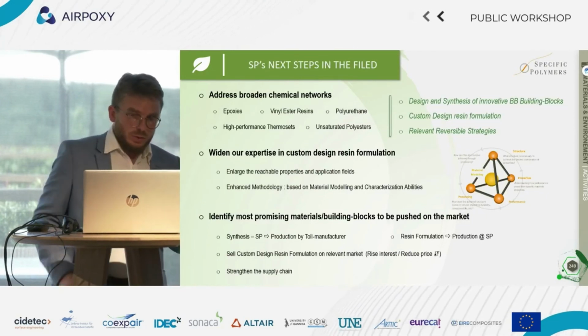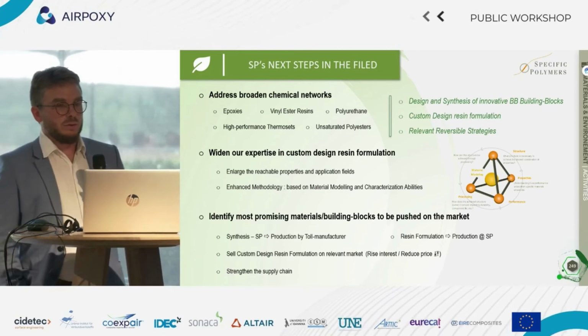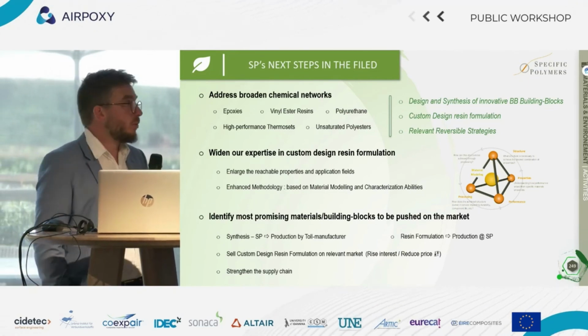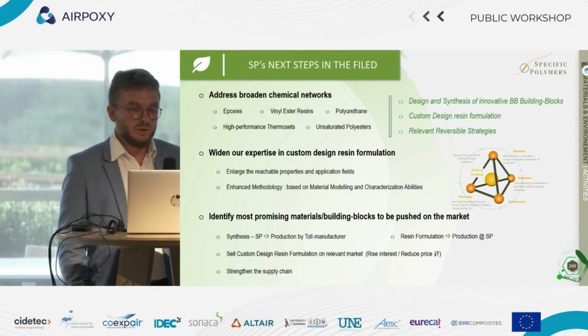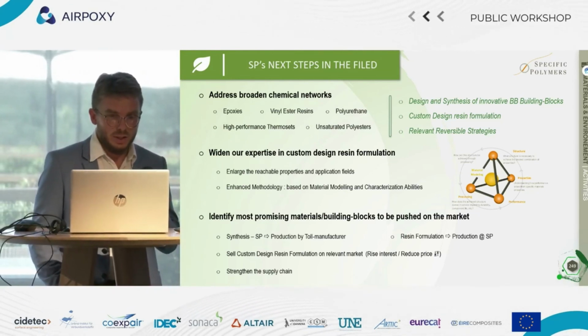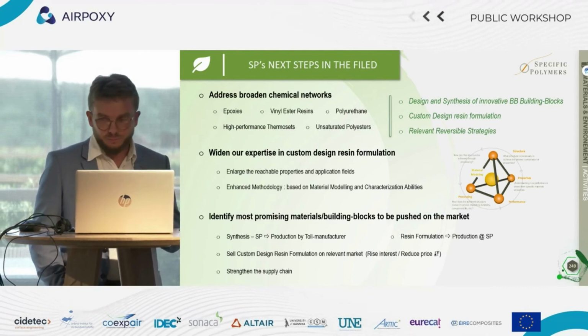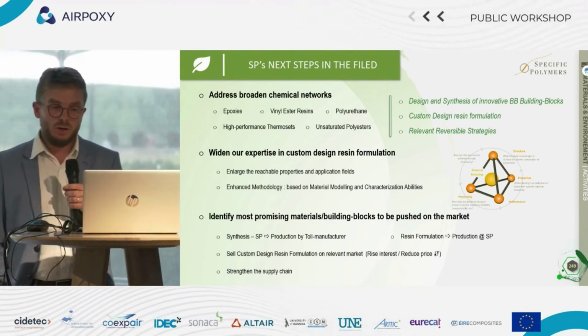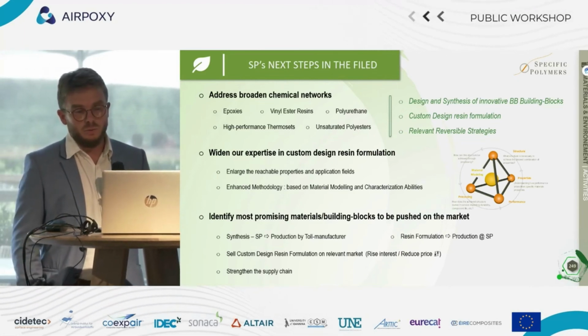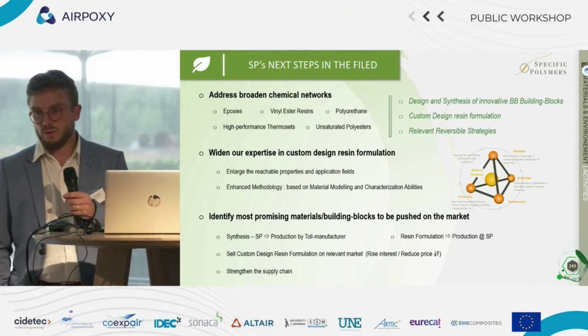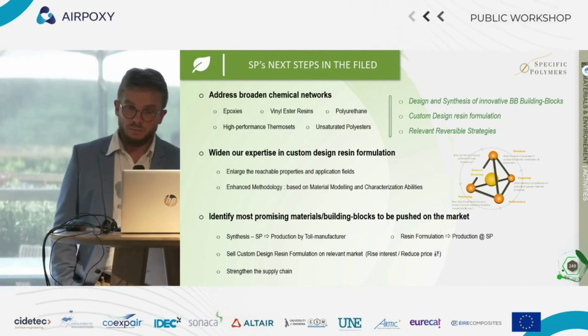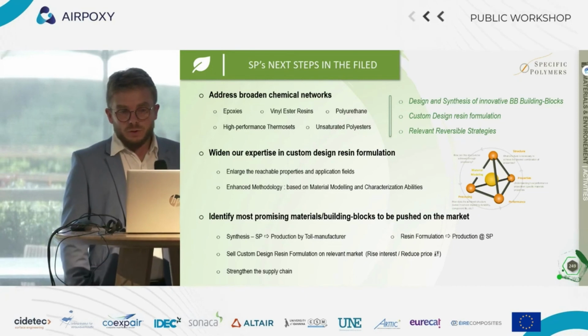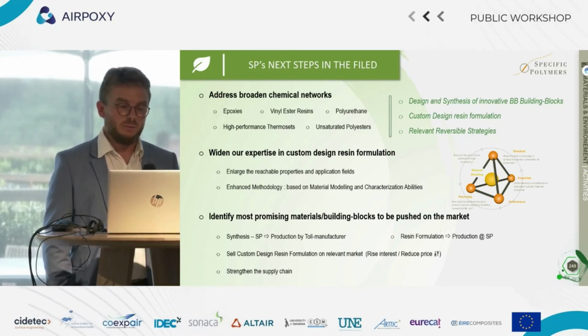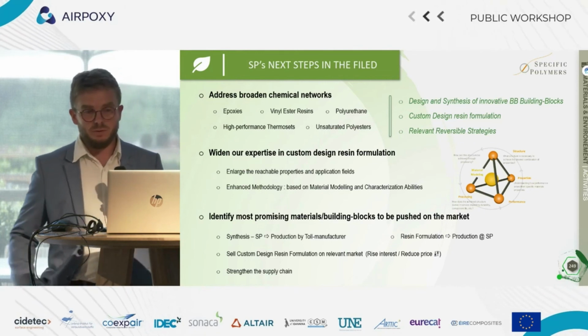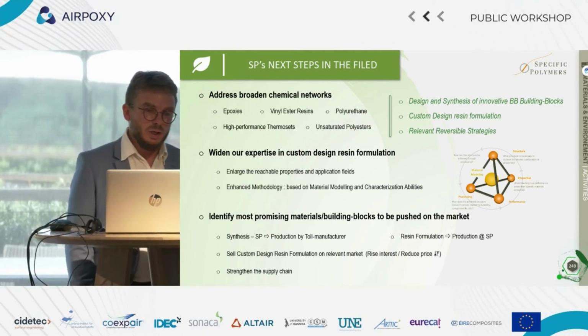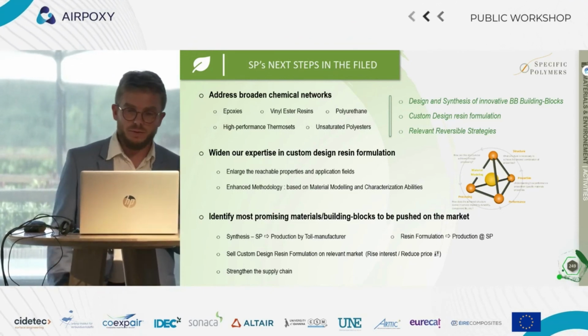So to finish my talk, just to give you an idea of what would be the next step for specific polymers. So first, we would like to address more and more thermoset resins. So we are working on epoxies, on vinyl esters, and unsaturated polyester resin. As it was mentioned, it's important to address higher performance materials. And so we already reached 200 degrees TG, but there is some specification at 300 and maybe more. And so first trying to go bio-based on this part, but if we want to go on reversible and high performance, when I say high performance, I mean 300 degree TG, it will be difficult because of the chemistry of the reversible bonds.